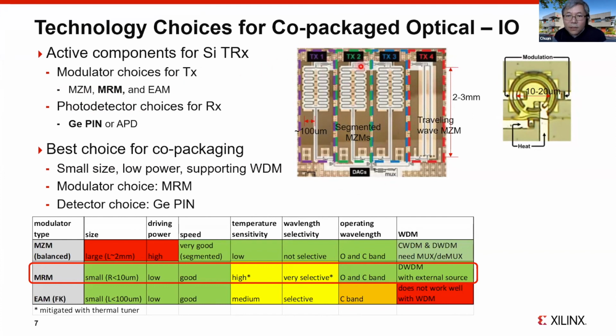Here I have a little picture showing 2 types of MZMs on the same die. On the left-hand side, you see 3 folded MZMs. These are segmented MZMs. Because of the large size of the modulator, you can't treat it as a lumped component anymore. So one way to design a high-speed modulator is to separate the long arms of the modulator into different sections, drive each section separately, and control the relative delay so that you can achieve high modulation at high speed.